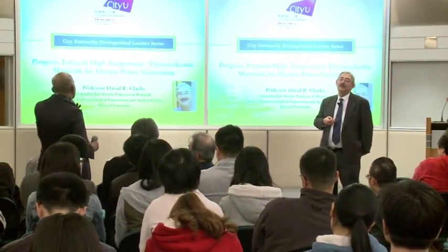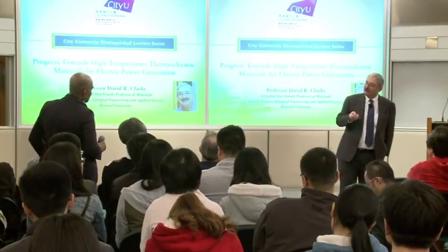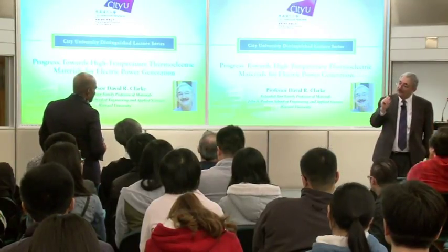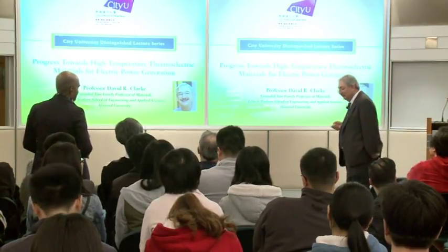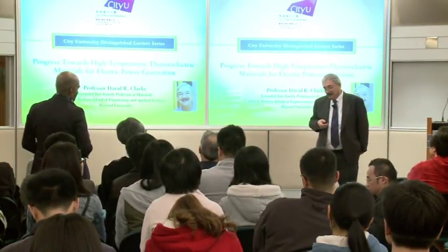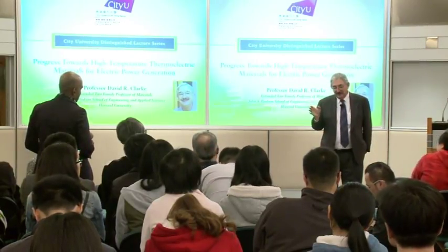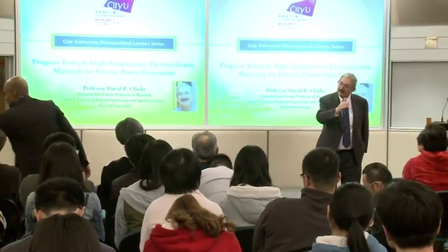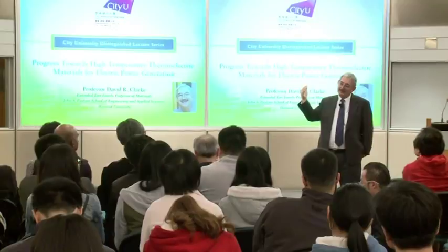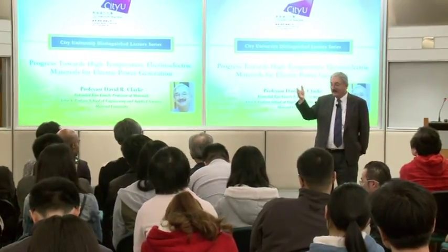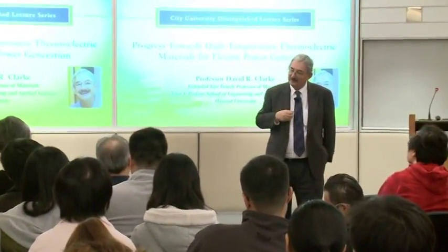Yes, I'm not sure that people have actually used zinc oxide as a semiconductor very extensively, but we know how to dope the material. We don't know what the optimum doping in zinc oxide is. Antimony is one, it's a 5+ ion, so it goes in. But the advantage of being able to dope the grains separately from the interface between the zinc oxide and the indium oxide gives us an added degree of freedom that you don't have.